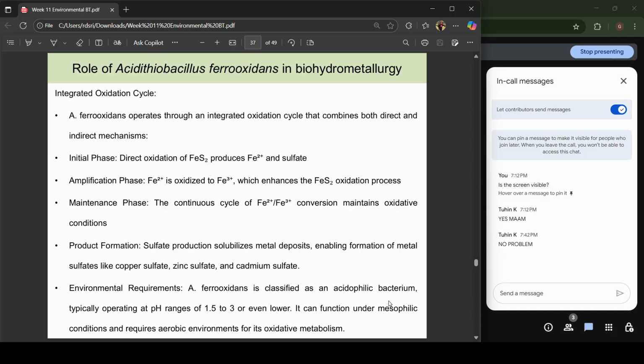So this Acidithiobacillus operates through an integrated oxidation cycle which combines both the direct and indirect mechanisms. In the initial phase there is going to be direct oxidation of FeS2 to produce sulfate and Fe2+ ions, and in the amplification phase this Fe2+ is oxidized to Fe3+, and in the maintenance phase there's going to be a continuous cycle of Fe2+ Fe3+ conversion which maintains the oxidative conditions.